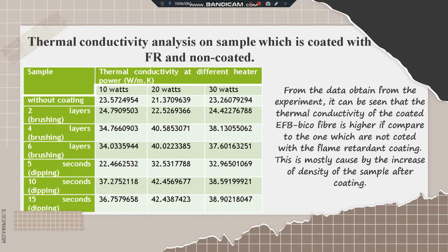Okay, from the data obtained from the experiments, it can be seen that the thermal conductivity of the coated empty fruit bunch microfiber is higher compared to the one which is not coated with the flame retardant coating. This is mostly caused by the increase of density of the sample after coating, where a solid object can conduct more, or can have a better thermal conductivity, compared to a material which has spaces between them in their arrangement of molecular structure.